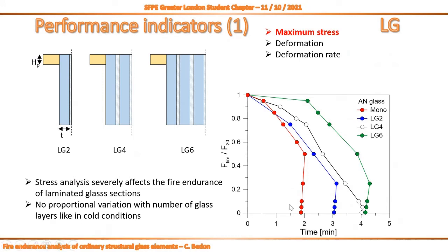So what happens again if we check the first stress value, which can suggest for us the fracture collapse of the beam? You can easily see from this chart, there is no more a linear proportionality between the number of layers and, let's say, the loading configuration. And this is true especially when we have a very big mechanical load for the section to verify. So a mechanical load which gives us a tensile stress in the bottom very close to the resistance of the basic material in combination with fire.